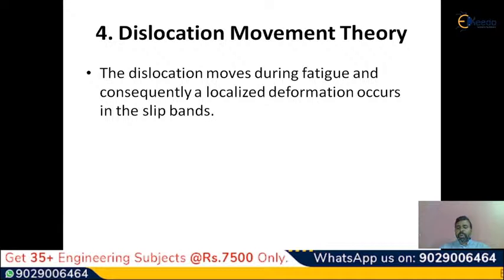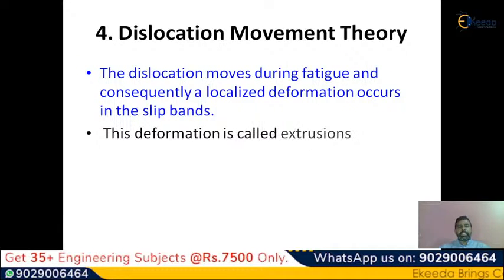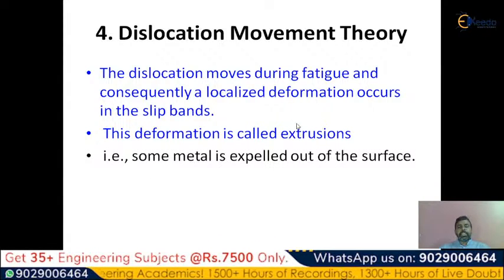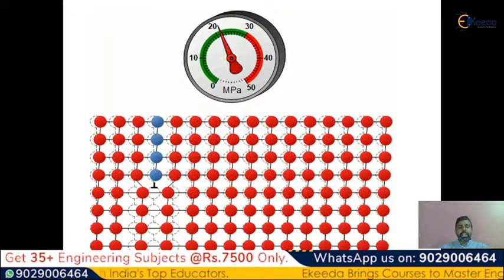Here the localized deformation will happen. So let me explain this dislocation movement theory. Whatever deformation is observed in the material because of the dislocations is called extrusions. What do you mean by extrusions? Due to this dislocation movement, some metal is expelled out of the surface. If any metal is expelled out of the surface, then that can be represented as an extrusion because of the dislocation movement. So please observe the image here.